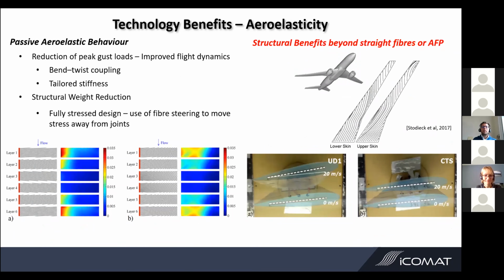Another benefit that we can enable is aeroelasticity. So what do I mean by that? Well, to make this kind of aeroelastic design, you really need to be able to tailor the fiber laminate and steer the fibers in plane. And what's been shown already in the wind tunnel is that the steered design has significant improvements compared to the traditional UD design. Specifically, it's got significantly lower deflection under load in the wind tunnel, and also the optimized design is able to keep the angle of attack constant under load, and this has a really drastic improvement on the flight dynamics of the aircraft.